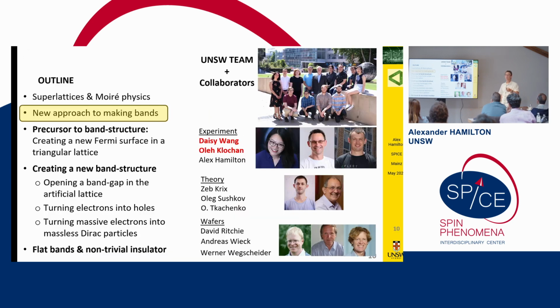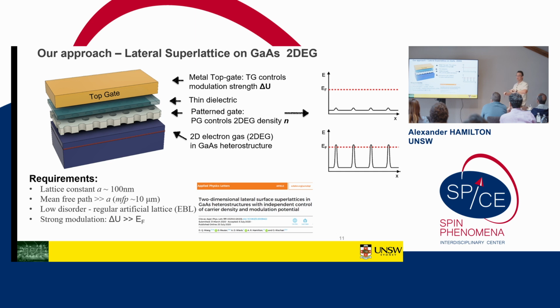So we wanted a new, more flexible approach to making artificial bands, and so that's what I want to talk about next. Our approach is just, let's use transistors. The industry is very good at these. We've been working on transistors for many years. So we have a high mobility two-dimensional electron system in gallium arsenide. We have a gate into which we pattern a periodic lattice, and then a dielectric, and then another gate on top. The combination of these two gates allows us to change the strength of the lattice potential and the chemical potential independently. So we can go from very weak modulation to very strong modulation.